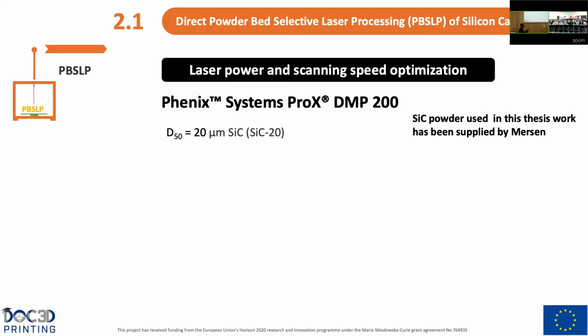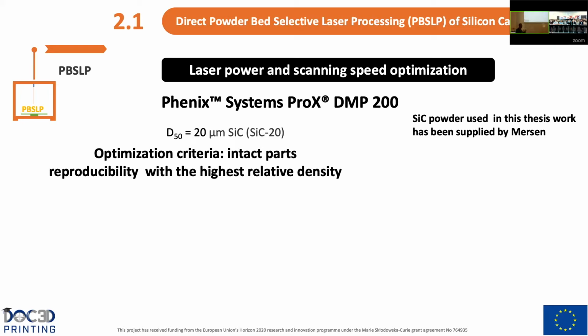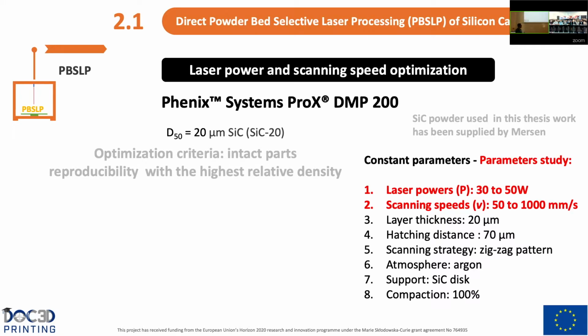So now, regarding the first experimental part, the optimization of the parameters of the powder bed selective laser processing, we were using 20 micrometer silicon carbide powder, and all the silicon carbide powder used in this thesis has been supplied by Mersen. As optimization criteria of the parameters, we want to achieve the highest reproducibility of intact parts with the highest relative density at the end of the process. Here we can see in black the constant parameters of the process, and in red the parameters of the study that we delimited in a previous study.